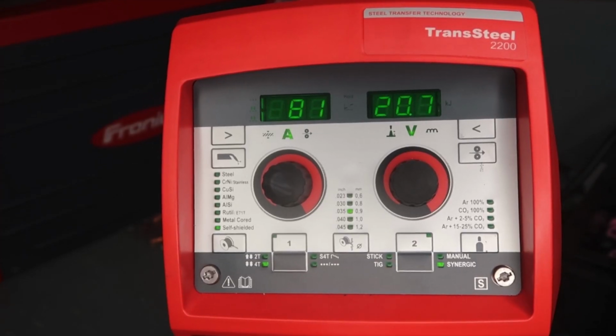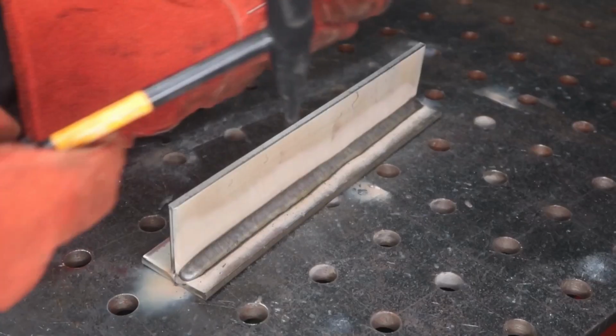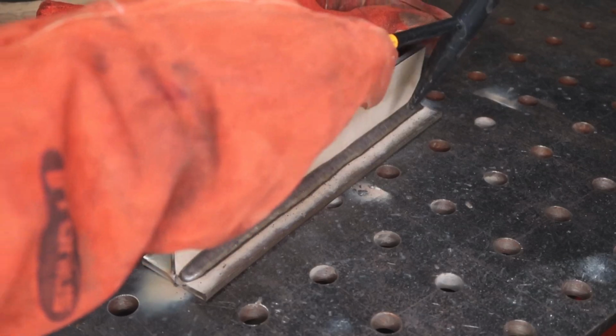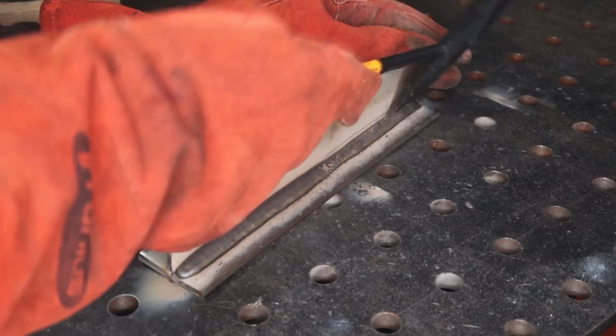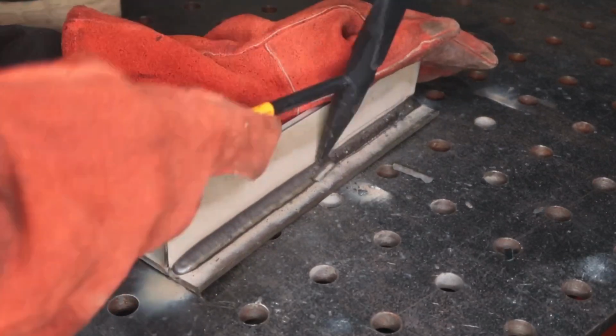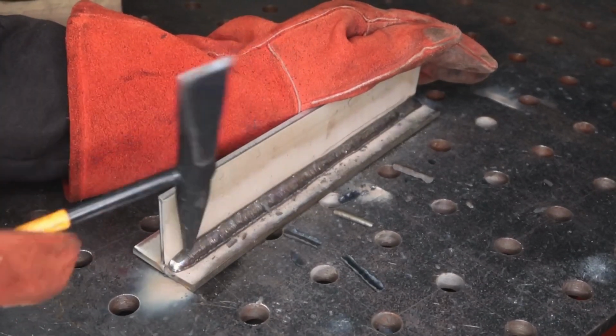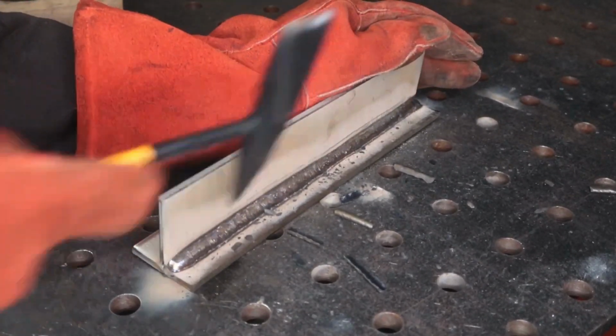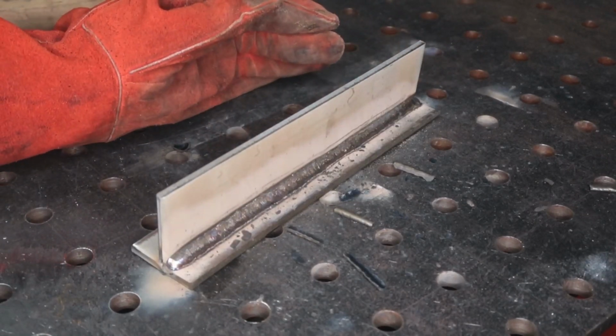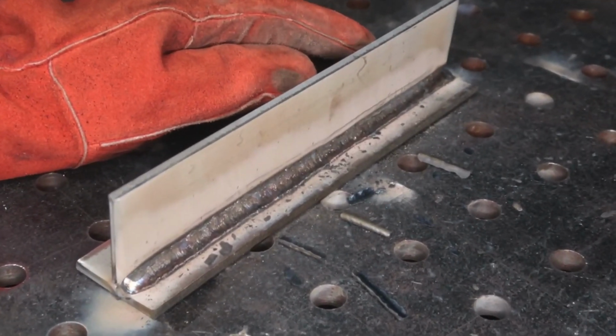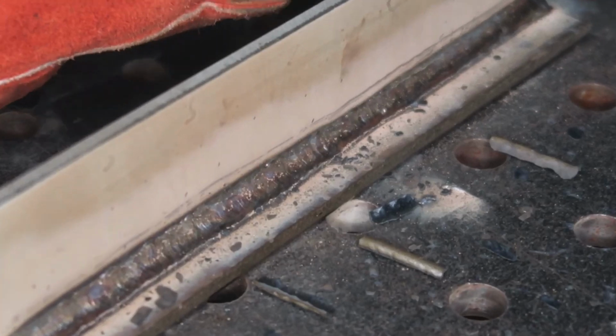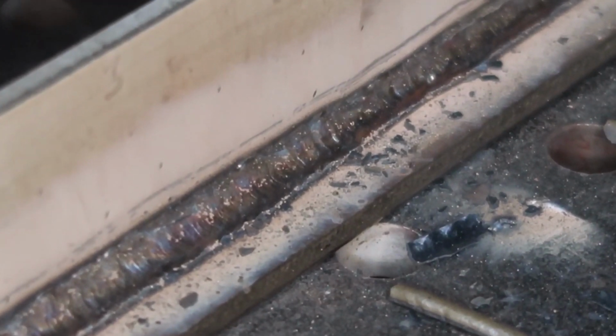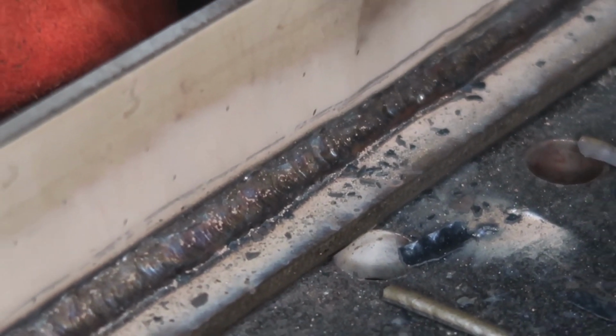And keep in mind, this is on 110 volt in the self-shielded program, but in electrode positive on the TransSteel 2200. Go ahead and knock this flux off the quarter inch stainless steel. It welds surprisingly good for a self-shielded flux core on stainless. If I was gonna be doing any portable work, especially 300 or 400 series stainless, I'd definitely be looking at this wire.